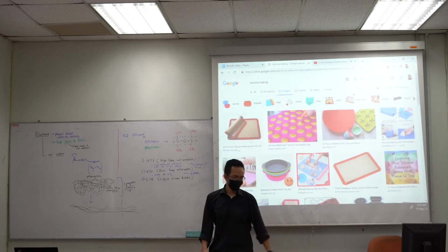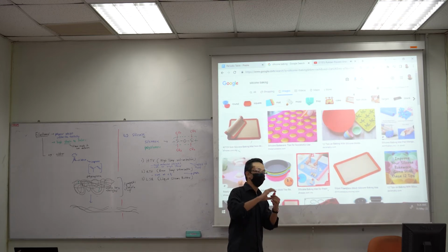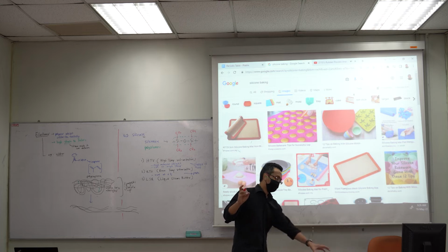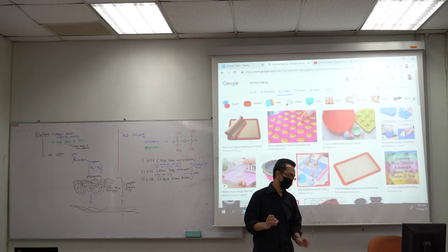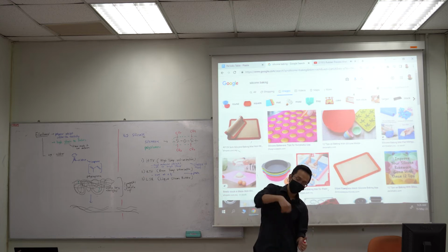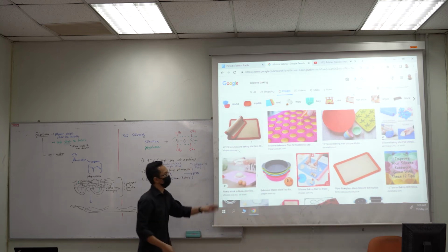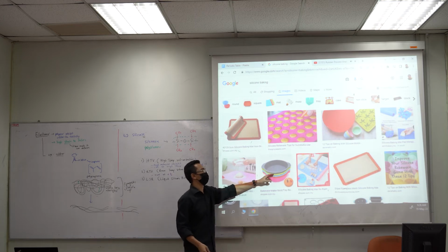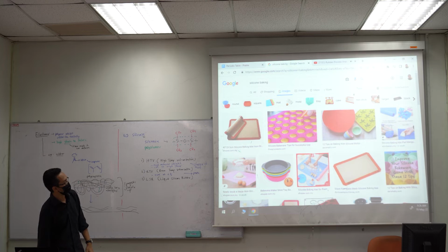Normally this liquid silicone has what we call a catalyst. By itself it is still liquid. You add this, only then it starts to harden, it starts to cure. So normally people have a cup, pour this in, then pour a little bit of the catalyst depending on the ratio, and then mix, and pour into the mold. Over time, because it's already mixed, the reaction happens, the silicone hardens, and lastly you get something like this. So that is a liquid rubber, liquid rubber silicone.